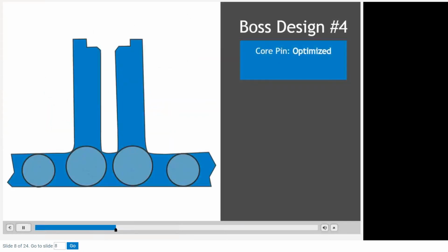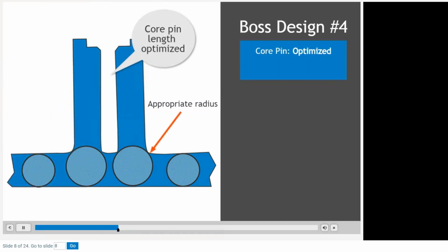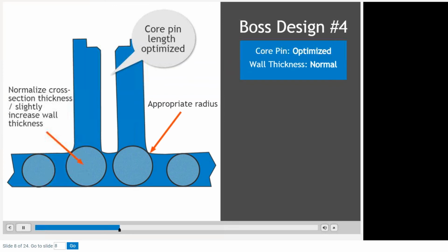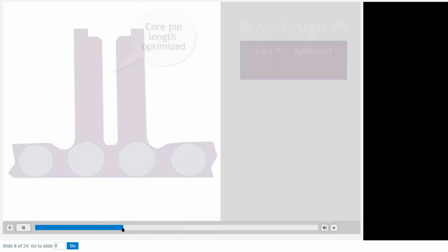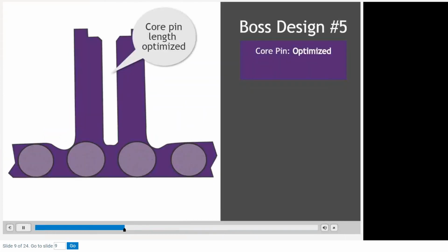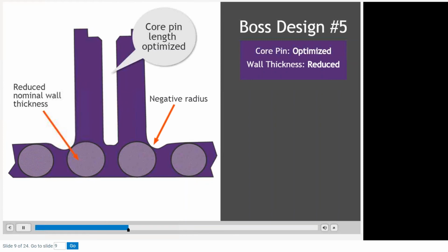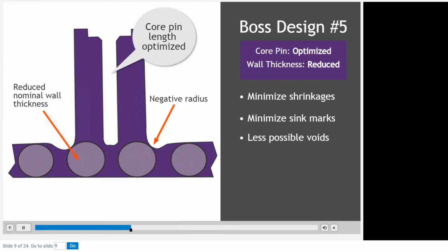The boss design here indicates that the core pin length was optimized, but this time an appropriate radius was added. This would normalize the cross-section thickness and slightly increase the wall thickness. Lastly, this boss design features a reduction in the nominal wall thickness and a negative radius. This design would reduce wall thickness in the cross-section area and could be an option for minimizing shrinkages, sink marks, and voids. Keep in mind, however, that by reducing wall thickness, a part will have less stiffness and strength.